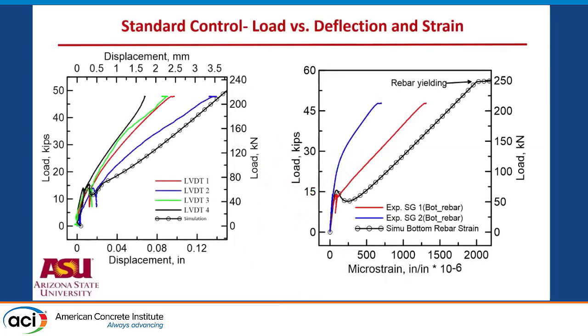Of course, what we have done is we've done the simulation and calculation for these systems. Again, you can see that the simulation relatively well predicts it. We're not into curve fitting. Your model has to be completely independent of the test result, which means that we're still slightly off. But then when we compare the load deflection shown on the left versus load versus the rebar strain, we see that we're getting a very reasonable result. The rebar is carrying the load, and that load carrying capacity occurs only after the matrix cracks and the load is transferred to the rebar.